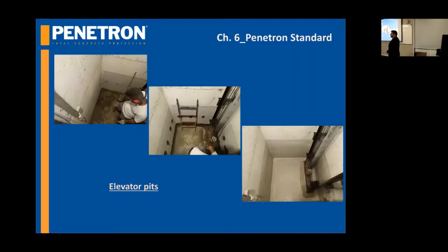This is an elevator pit. Elevator pits have a lot of problems because they are typically the lowest part of a building. If water finds a way, water is lazy, it finds the easiest way to pass. Elevator pits are something like a highway for water. So in this case, it has been repaired, especially the joint between the foundation of the pit and the wall, and it has been repaired with Penetron and mortar with Penetron inside.